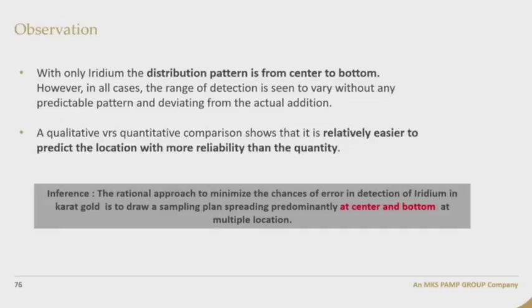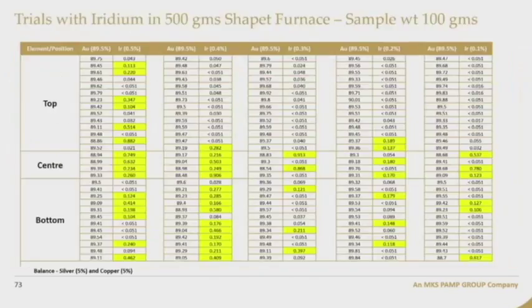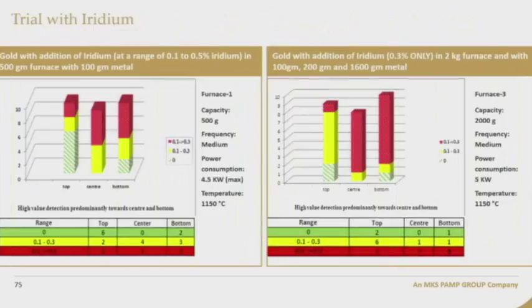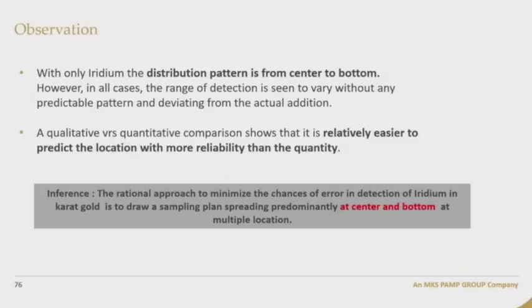However, in all cases, the range of detection seems to vary without any predictable pattern, deviating from the actual addition. We added 0.5, but we could find 0.75, 0.6%. So this was not exactly what we added. The qualitative and quantitative comparison shows that it is easier to predict the location with more reliability than the quantity. So what do we infer? We infer that the rational approach to minimize the chances of error in detection of iridium in carat gold is to draw a sampling plan spreading predominantly at center and bottom and at multiple locations.